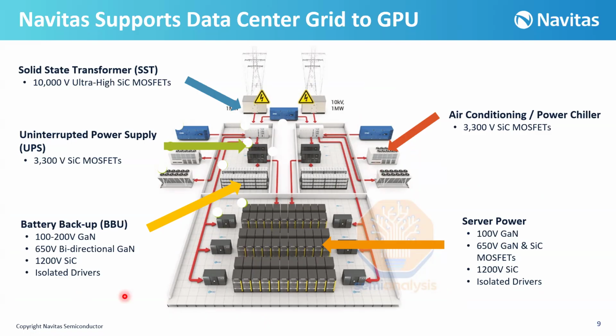As an example, we have the 100, 200 volt gallium nitride, and also 650 volt bidirectional gallium nitride. And also we have 650 volt silicon carbide up to 10 kilovolt and even higher for the silicon carbide. And by this, we can support the different parts of the grid, the data center grid to GPU, in SST, in UPS, BBU, air conditioning and power chill, and server power.